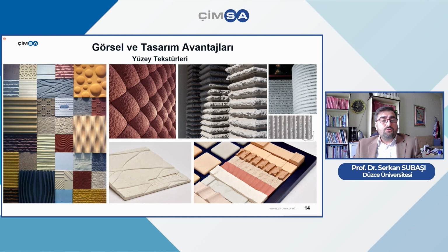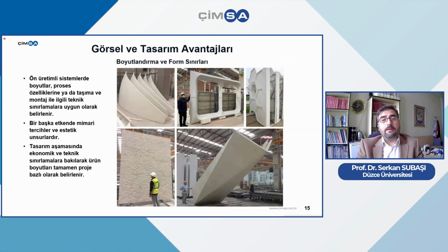The surface texture is a very important feature of it. I mean, the surface texture is related with the molding technology. Any type of surface texture is possible to shape in glass fiber reinforced concrete, and the molding applications, starting from the wooden mold and also polyester, polyethylene, different types of molding types can be used during the production processes. The thickness, the depth, and the size of the molds are changing. And when we look at the sizing of the forms, up until now, it is an extraordinary, wide-scaled, and also a very thin layered type of product. So it's a very special type of concrete which is being produced.